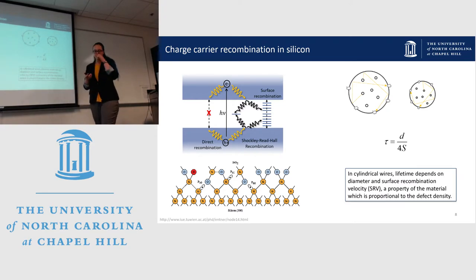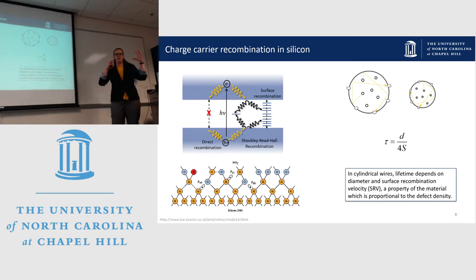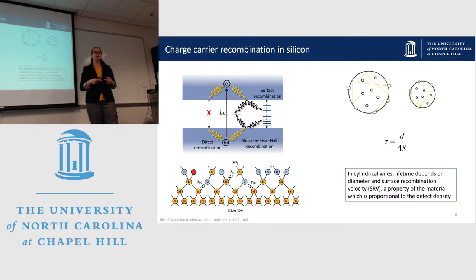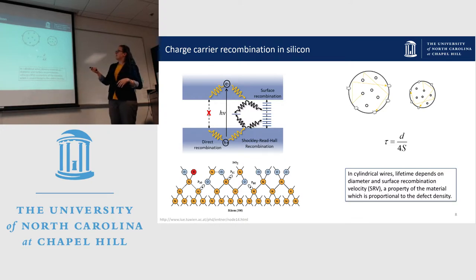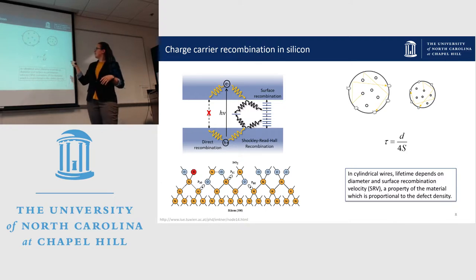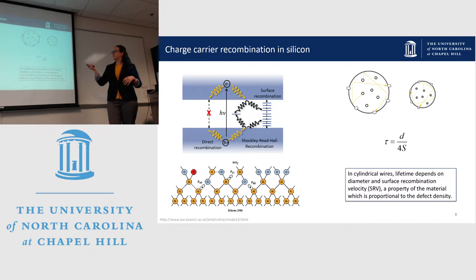Sorry about that. Because these are all at the surface, there's something else that impacts the lifetime, and that's the diameter of the wire. So we're exciting carriers all throughout the wire, but they have to make it to the surface before they can recombine. So if the diameter is larger, they have to travel farther, and it takes them a longer time to recombine than if the diameter is small. So this means that the lifetime is proportional to the diameter. And what this expression tells us is there's a relationship between diameter, lifetime, and S. And if we measure the lifetime and we measure the diameter, it means we can calculate S. So now we have a way where we can measure how good the surface of a nanowire is.